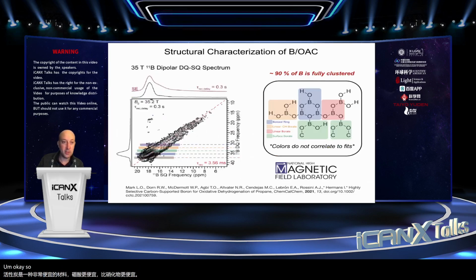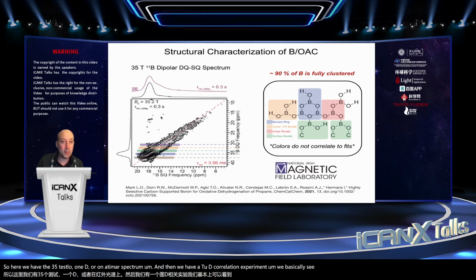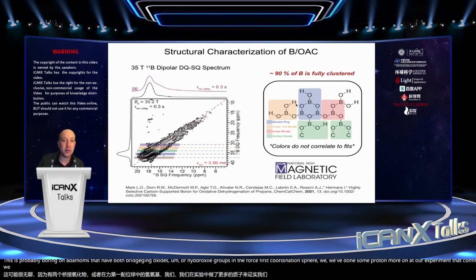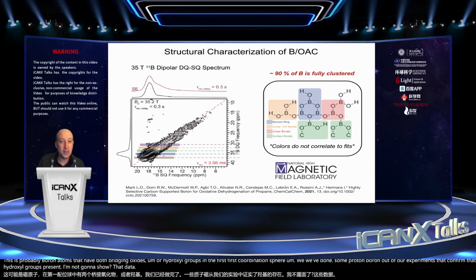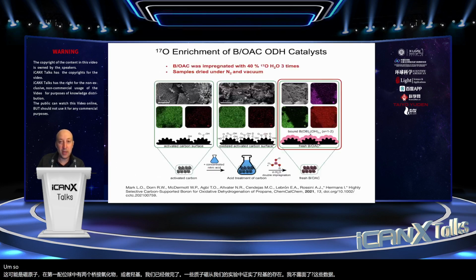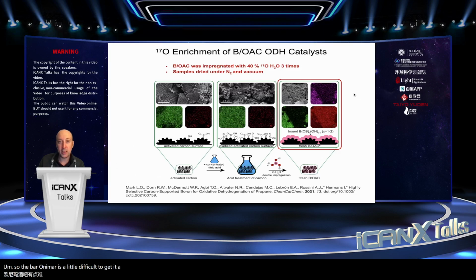Okay, so what do we think is going on? Now we can turn to the NMR data to try to understand the structure of the boron atoms in this material. So here we have the 35 Tesla 1D boron NMR spectrum, and then we have a 2D correlation experiment. We basically see one boron signal. This is probably boron atoms that have both bridging oxides or hydroxyl groups in the first coordination sphere. We've done some proton-boron NMR experiments to confirm that we have hydroxyl groups present. I'm not going to show that data. So the boron NMR is a little difficult to get a clear picture of this material.